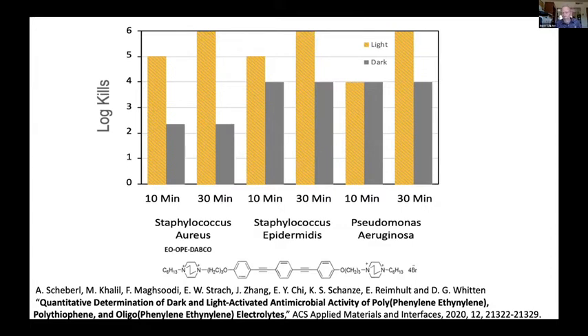But here we focused on how complete the activity is, because people don't want even a trace left. For example, with Staph aureus, we found that with 30 minutes, we had 6 log kills. That means there's essentially nothing; by doing serial dilutions, we found there was no survival beyond a certain point. Then we tried 10 minutes, which is shorter. Even with all of these in the light, shown by the light bar, and to some extent in the dark, you get really astonishing killing of these bacterial pathogens.